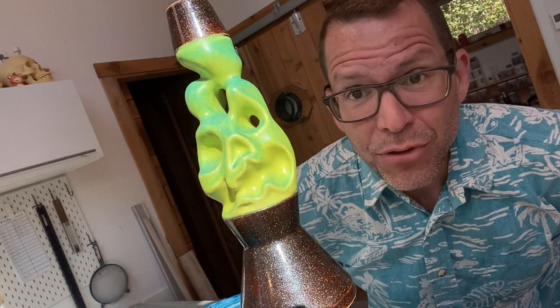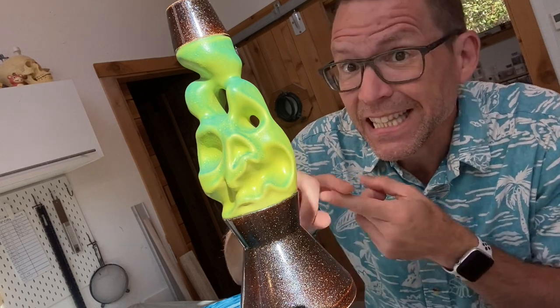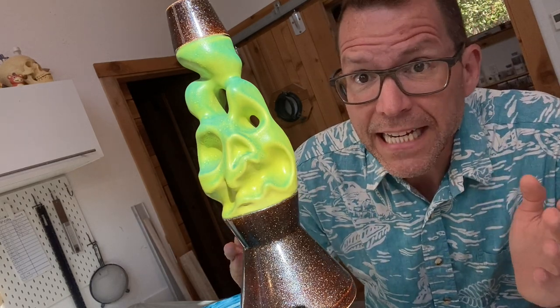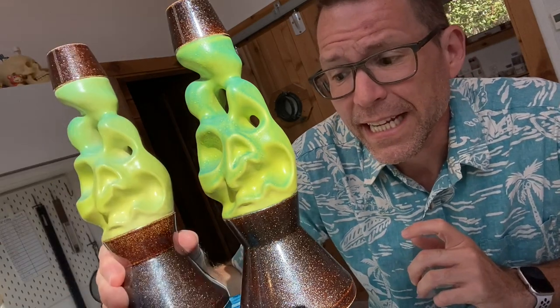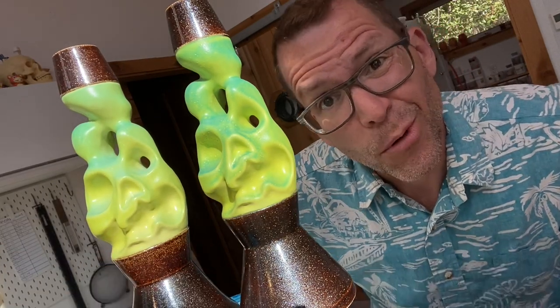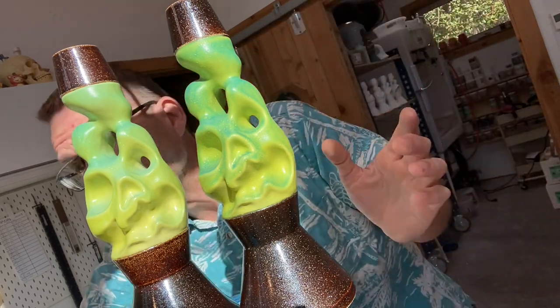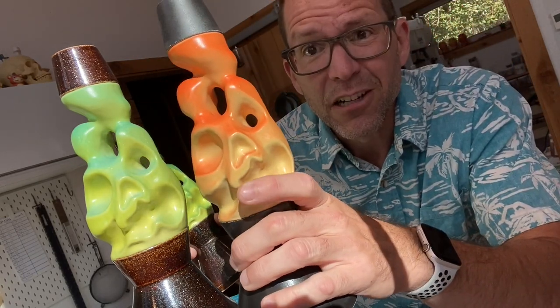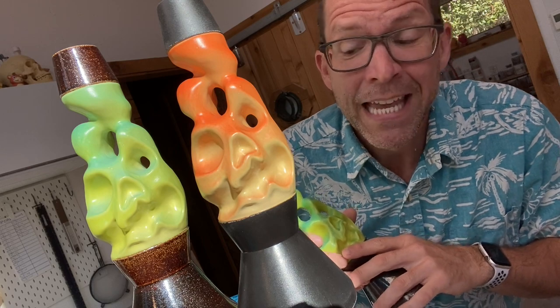So there are lots of variables that can affect a firing and cause pinholes like we have on this glaze test. So I went through and did another one trying to eliminate all those things. I cleaned my bisque ware, I was extremely careful in the application, I did very light coats — lots of stuff to try to alleviate it. Unfortunately, it had the exact same issues. We redid the red and I actually tried a red and yellow, which not only did it look gross, it also had pinholes in it.